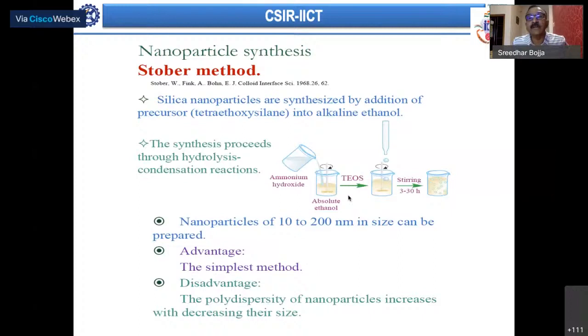We worked on silica nanoparticles to start with, using the Stober method, which is a rugged method. If viewers are interested, please make a note of this and go through it, because it's a very rugged method where you can synthesize particles of uniform size and uniform shape.